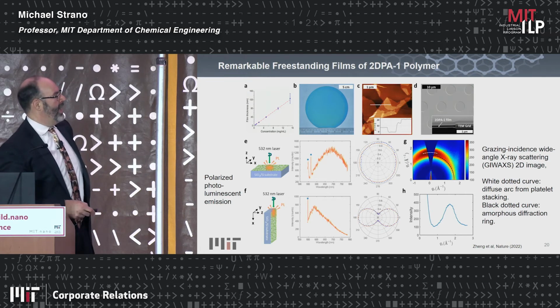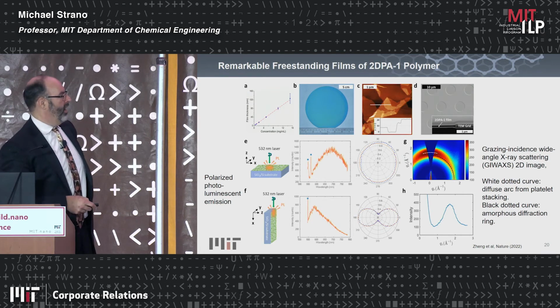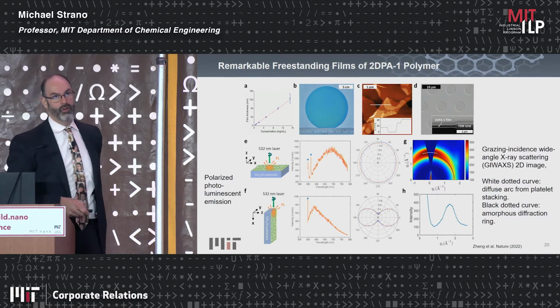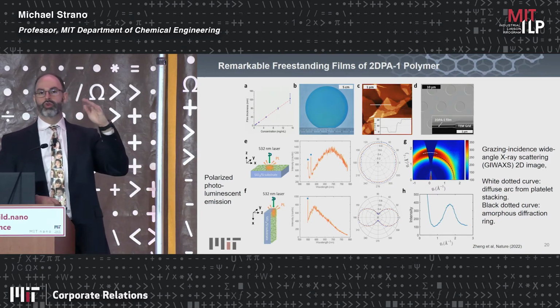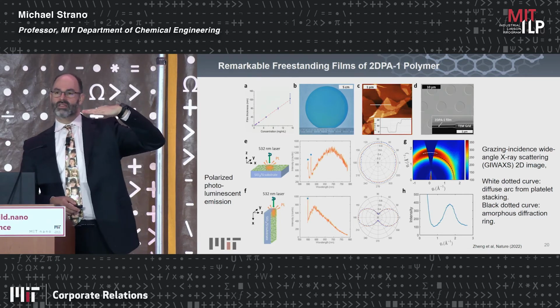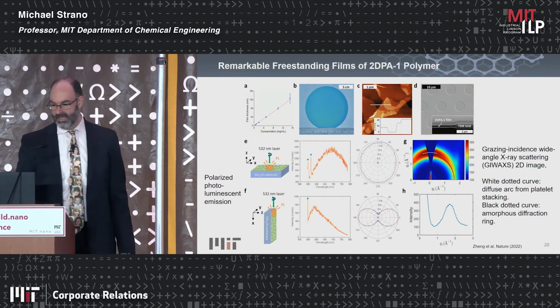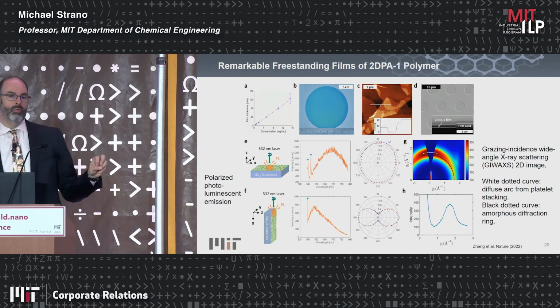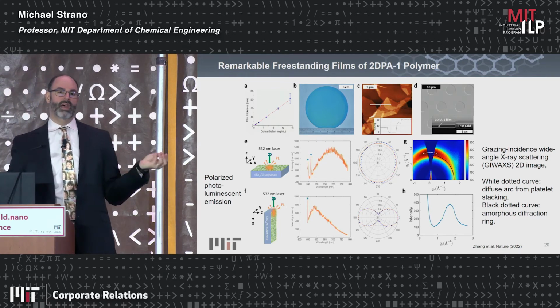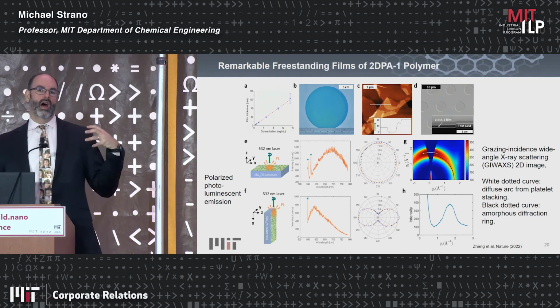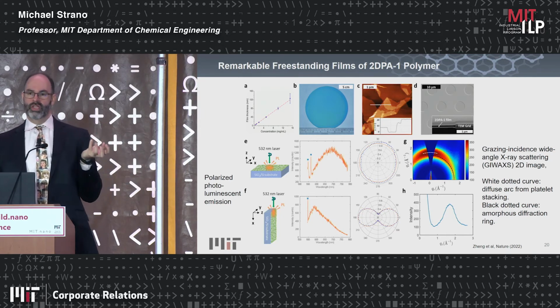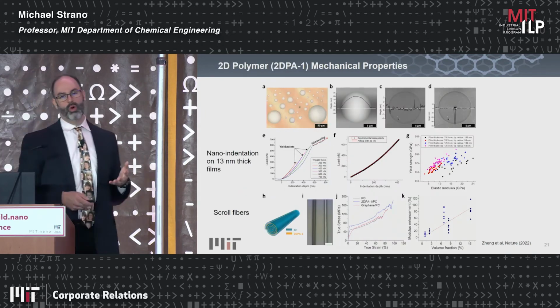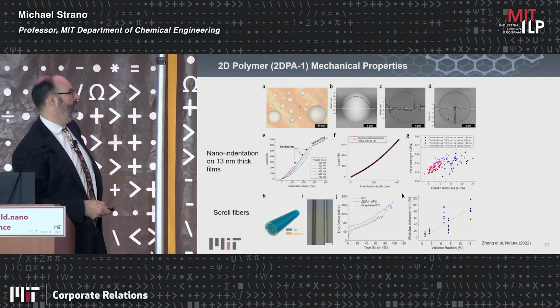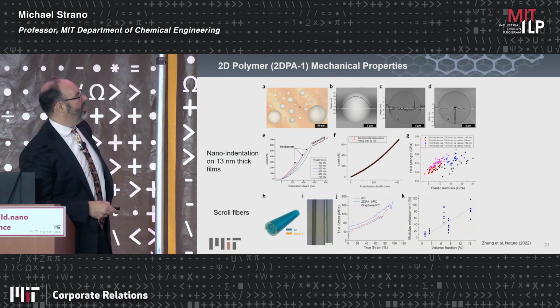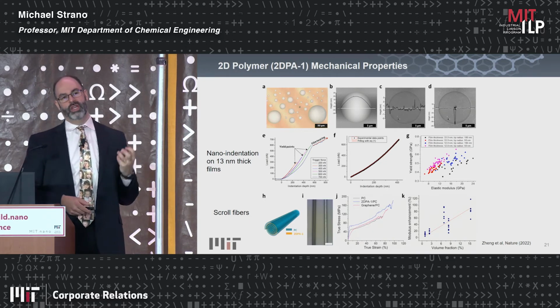You can use X-ray scattering of different kinds. You can use polarized fluorescence. On the bulk material, you can show that these platelets like to stick and align inside the thickness. And normally with a nanomaterial, it can take quite a bit of time to then scale this up. Can I make a material that's big enough to actually hold in your hand and you can study? But because we're polymerizing, we have that right here in this paper. So first, interestingly enough, we found that even at nanometer scale thickness, these materials are essentially impermeable.